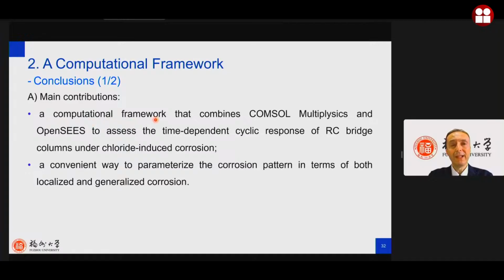So, to summarize, a computational framework that combines COMSOL Multiphysics and OpenSees to assess the time-dependent cyclic response of reinforced concrete bridge columns under chloride-induced corrosion is proposed. It can be quite time-consuming to simulate everything in COMSOL. So we are also thinking of a mixed system where some phenomena are simulated in COMSOL and others are obtained through data-driven simulation. So having many data, you obtain some law and you use that analytical law and you don't consider all the phenomena in COMSOL, to try to have an easier way to do it.